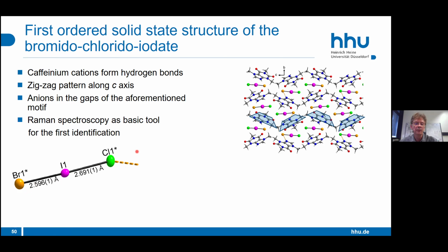trihalide which is really not disordered. Before, all the structures in the database, and it's only a handful of them, are disordered. But in our case, it's not disordered. Why is it important to have it not disordered? We need the bond lengths to estimate some bonding properties, perhaps to do some calculations, and to fit our results with the Raman spectrum.